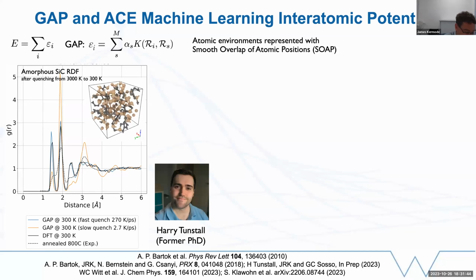So let me go step by step. The first thing we do is try to match DFT. So black here is our reference DFT quench. We can only do that very quickly. It's expensive to take a liquid and cool it down directly with density functional theory, so we have to cool it very fast. If we quench our GAP at the same speed, at high speed, in blue, we can see it matches reasonably well with what you get if you do this very rapid quench. But that's not very realistic. It doesn't really match what's done in experiments where the liquid is cooled much more slowly.